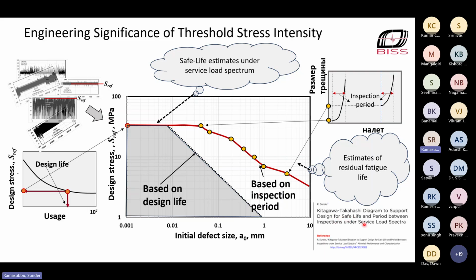about how to use these data to construct a Kitagawa-Takahashi diagram to support design for safe life and period between inspections. Essentially, on the vertical axis, you have the design stress for a structural element. On the horizontal axis, you have initial defect size. So depending on the defect size, your design stress level will have to be brought down for a finite life, service life. But if you're looking at inspection period, as long as you can detect a defect of this given size, you can increase the inspection period. And this is a key element in maintenance on condition.